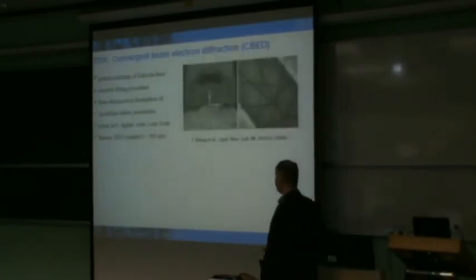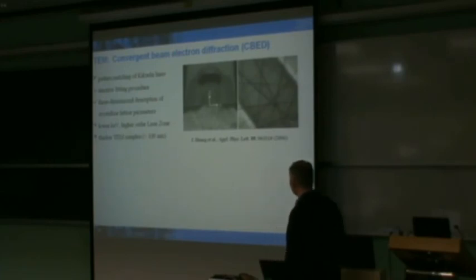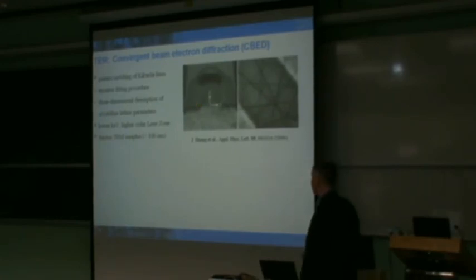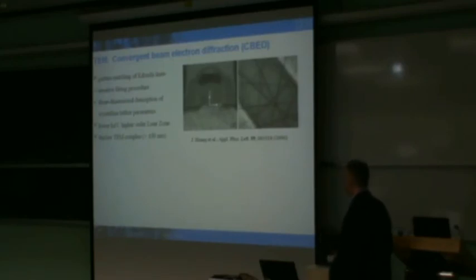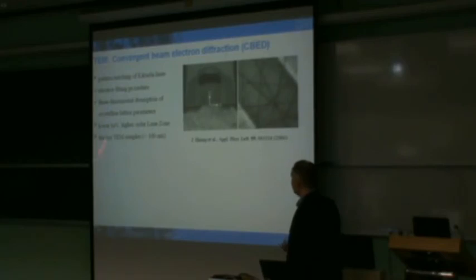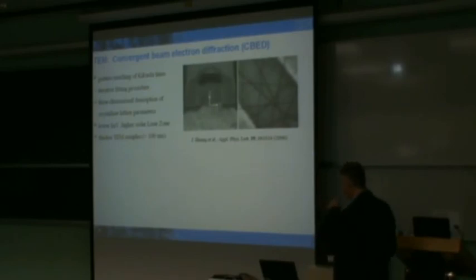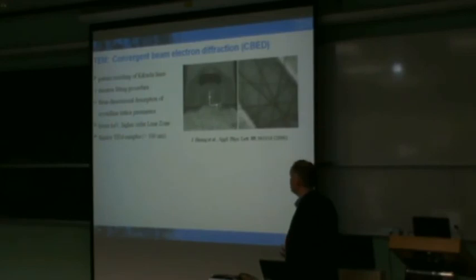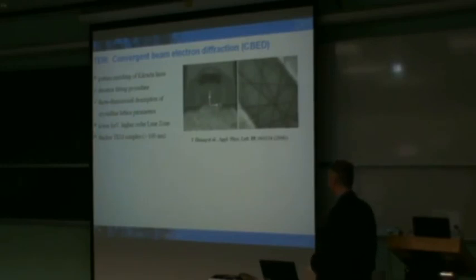Okay, so with the TEM-based techniques, one of the first ones that was developed and applied about 30 years ago was called convergent beam electron diffraction. For the sake of completeness, I included it here, but it's really not one that's incorporated that often anymore. Basically, you're looking at the Kikuchi lines that are generated. These are dynamic diffraction effects that exist because the electron beam is passing through the material. The nice thing is that through a fitting procedure, you can actually get a three-dimensional description of the lattice parameters at the point and place that you're interrogating. Typically, to do this, you use a lower operating voltage of your TEM than you do for imaging, and you use thicker TEM samples, and so the effects of elastic relaxation within the center of the structure are mitigated.